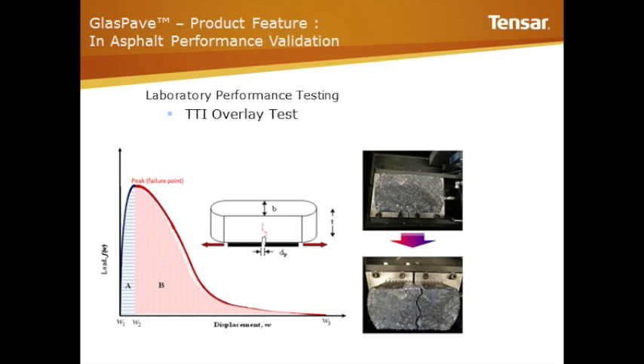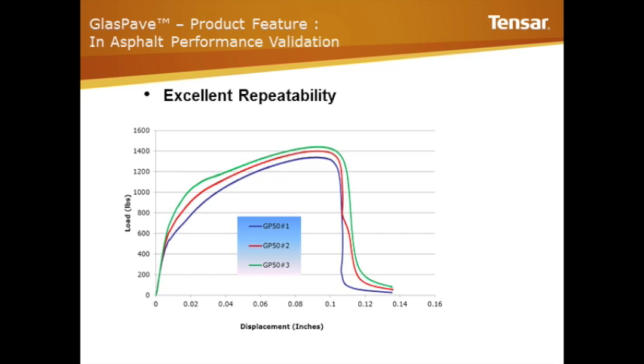So the nice thing about these tests is we can manufacture the specimen, a composite specimen, using a gyratory compactor. And so we also like the fact that we can produce a specimen with better repeatability. Typically, if you're manufacturing samples for interlayer testing, they're normally large specimens, and with a beam or slab, you can typically get plus or minus 4% air voids, which for reflective cracking is quite sad. And so ultimately, we really like the fact that we have better quality control. Now you can also take specimens from the field and test those, but ultimately we love the concept of this test.